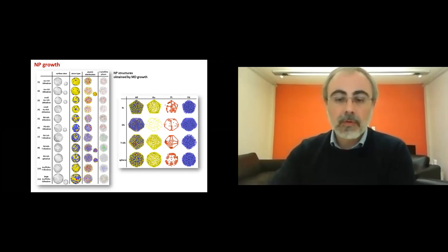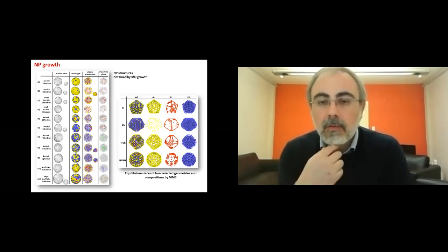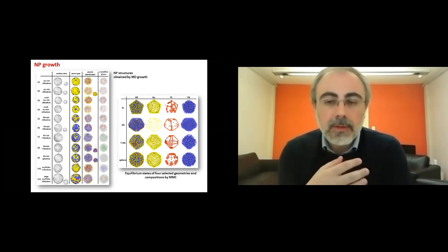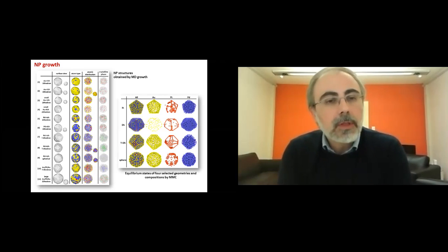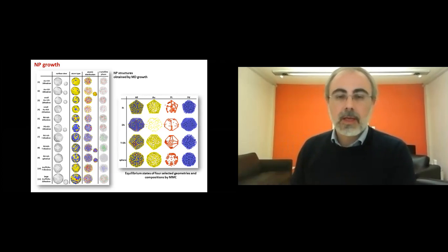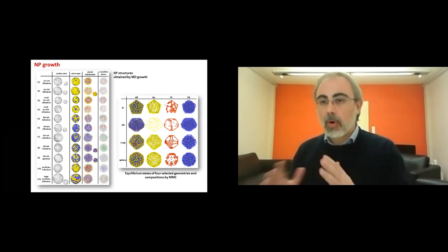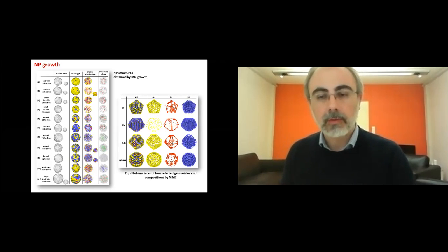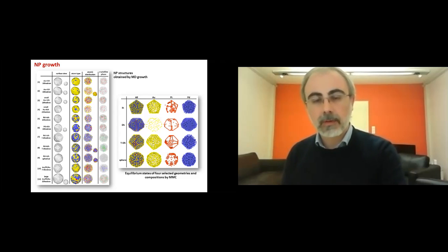And then we did Monte Carlo simulation to establish what are the equilibrium states for nanoparticles of our sizes. And we found that there was a good agreement, a relatively good agreement between our MD nanoparticles and the stable structures as obtained by Monte Carlo. And the main idea here is that our simulated nanoparticles managed more or less to reach equilibrium and to get the final structure which corresponds to the energetically favorable configuration.